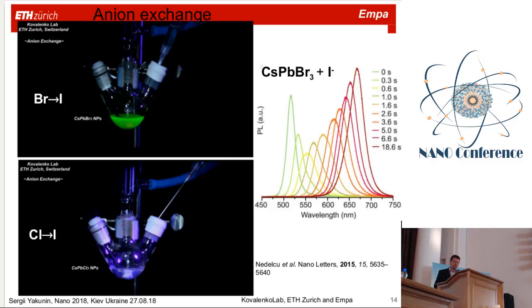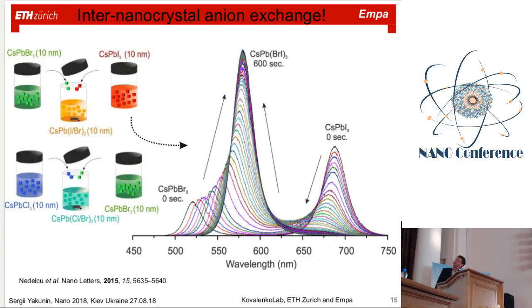So in principle, in a colloidal solution of perovskites, actually it should be a video, but I think it will not work in this case. Maybe not. But just believe me. So here was a demonstration where in a solution of colloidal perovskite nanocrystals, you add a precursor containing a high concentration of another halide, and simply it will change color within a few seconds. Another demonstration of the same feature of anion exchange is that if you mix a few different types of perovskite nanocrystals with different halide composition, they will interexchange their halides, and they will come up with just one common color.